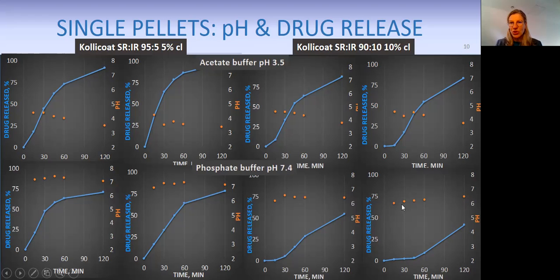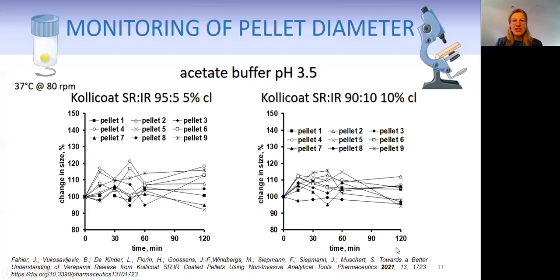So what we can conclude from this is that we've got differences in drug release between individual pellets, which is actually not quite often seen in diffusion controlled drug release. And we also have some lag times, meaning we have a different onset in drug release. So this needs further investigation. For example, we wanted to know this lag time.